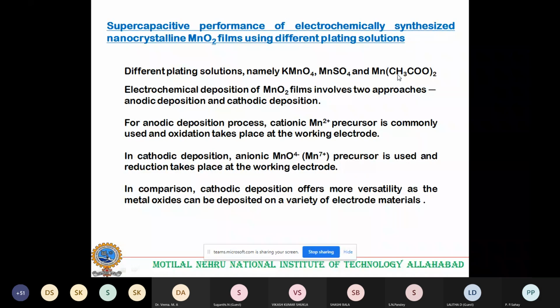Basically, the electrochemical deposition of MnO2 involves two approaches. One is the anodic deposition, and the other we call the cathodic deposition. For anodic deposition, a cationic precursor, that is manganese sulfate, Mn2+, is commonly used. That is MnSO4. And when it is cathodic deposition, the KMnO4 precursor is used. If you go through the literature to find out which is better, anodic or cathodic, the cathodic deposition offers more versatility, as the metal oxide can be deposited on a variety of electrode materials. So it is the preferred one, but a number of works have been done with the other also.